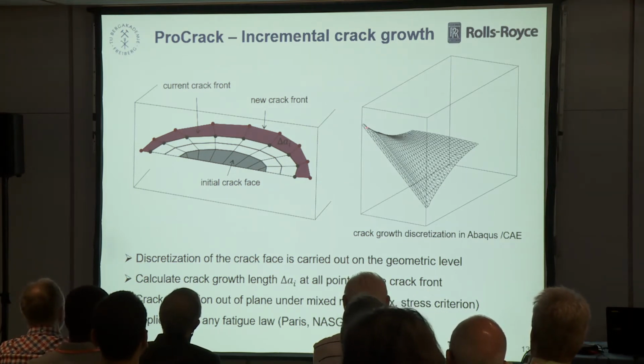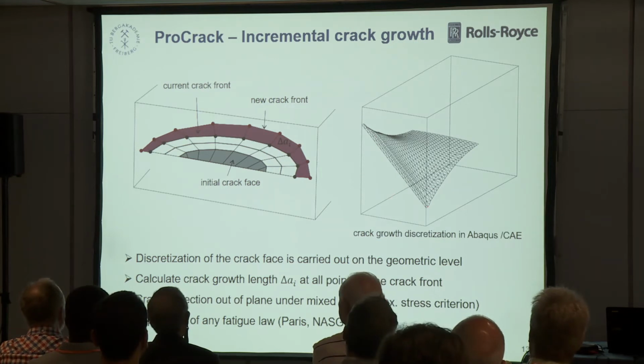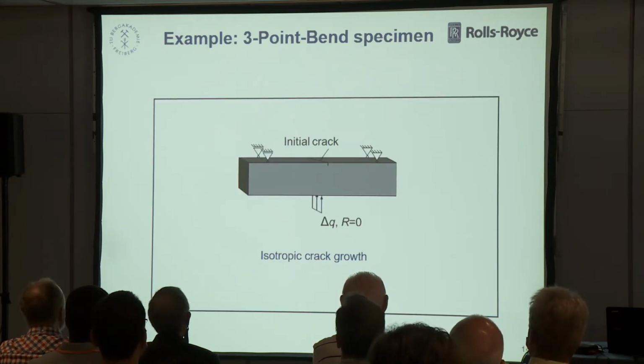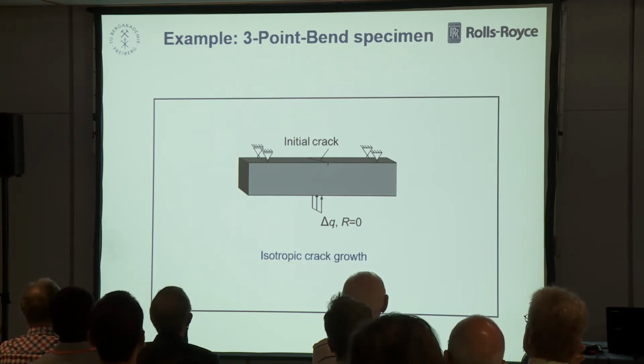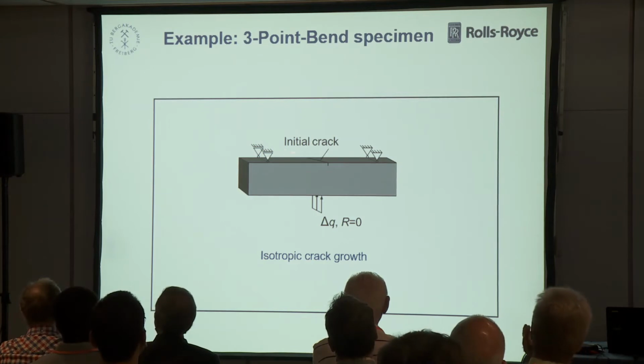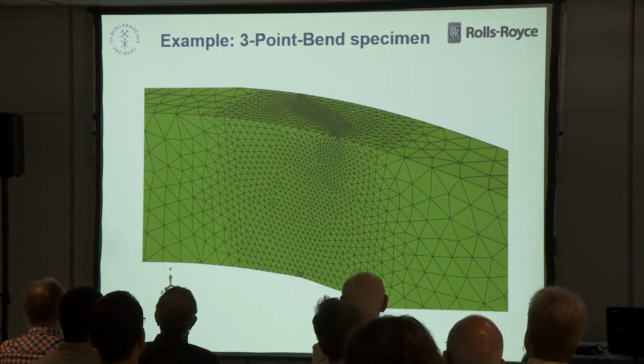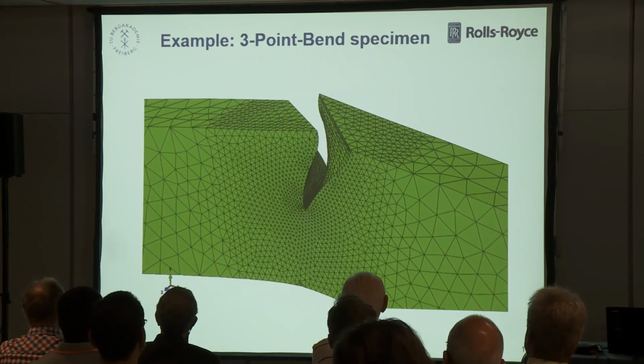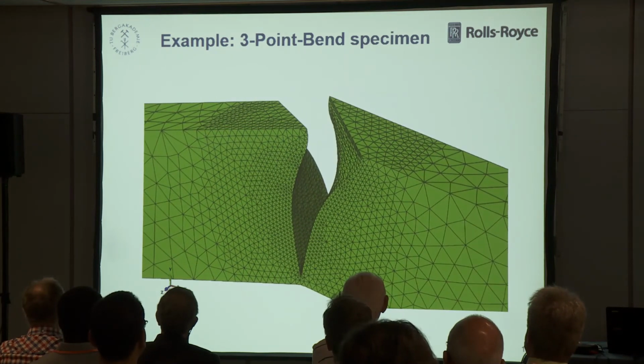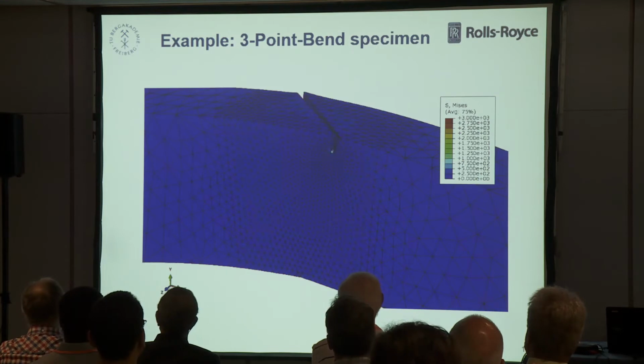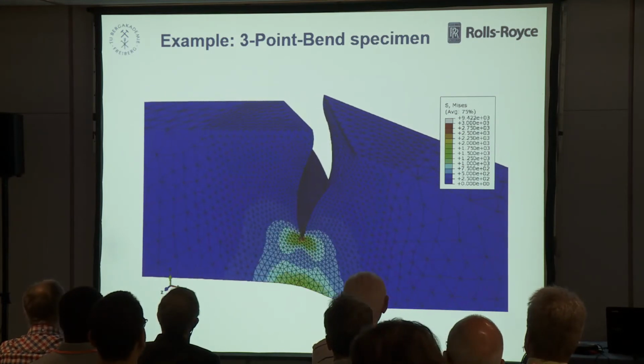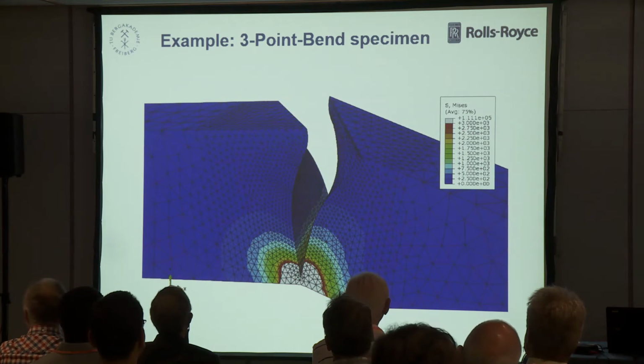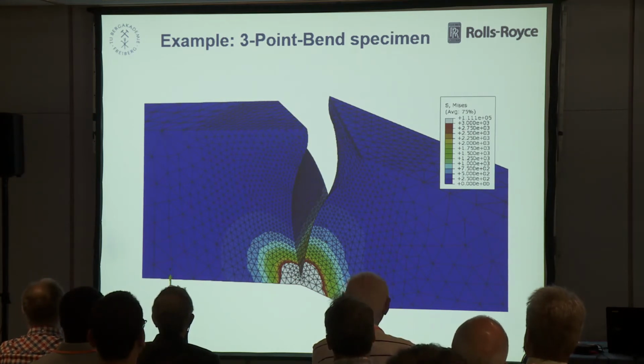So here you see how the curved crack form can evolve for this example. It is a classical benchmark problem for such cases, a three-point bend specimen, which has a crack which is inclined to the bending axis by 60 degrees. It starts from this inclination, and in this simulation, this is a global mesh. The crack turns into the direction of the symmetry line, perpendicular to the maximum principal stress. So it wants to find mode I solutions. These are the stresses.